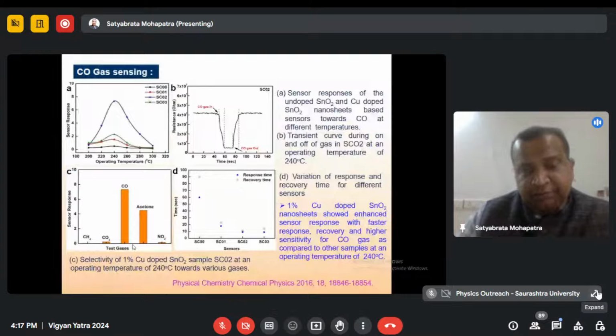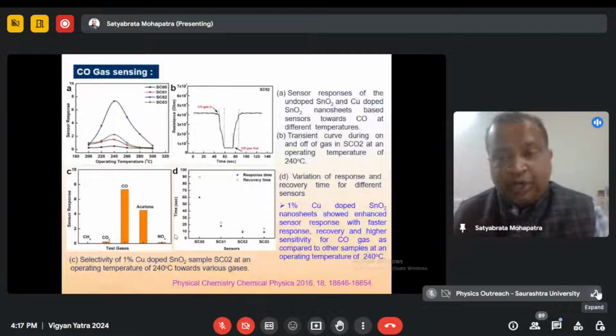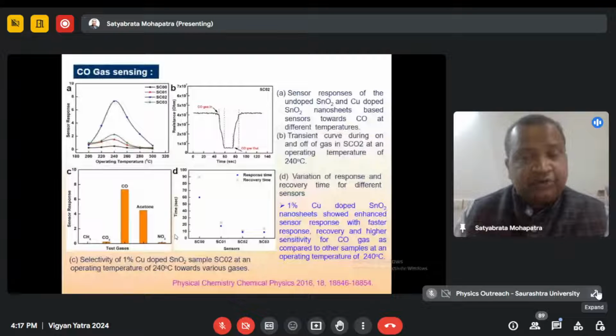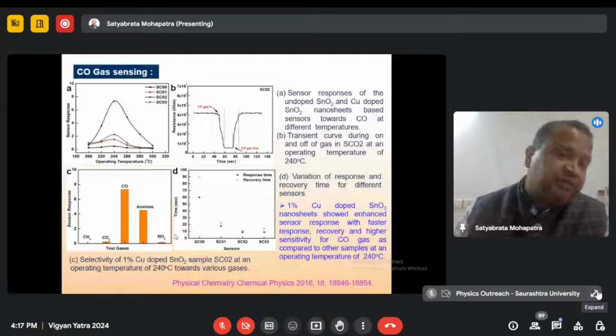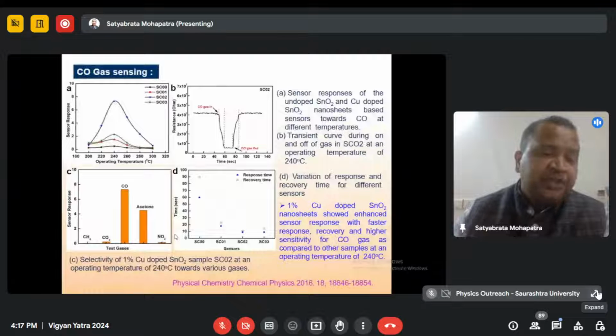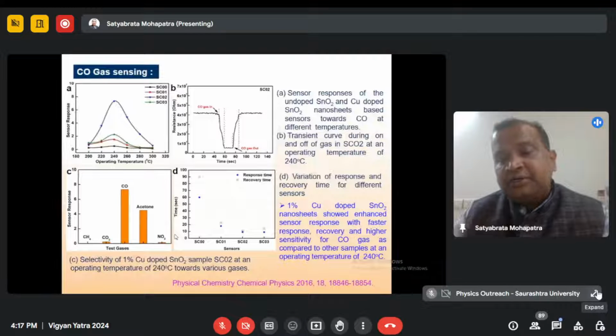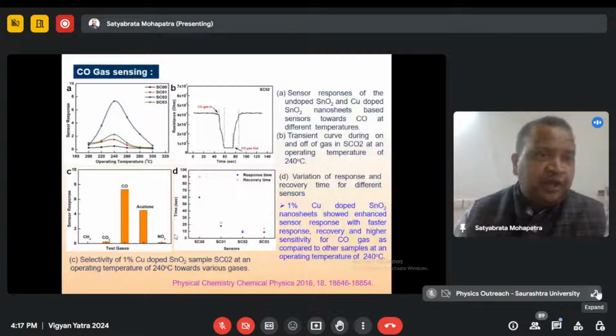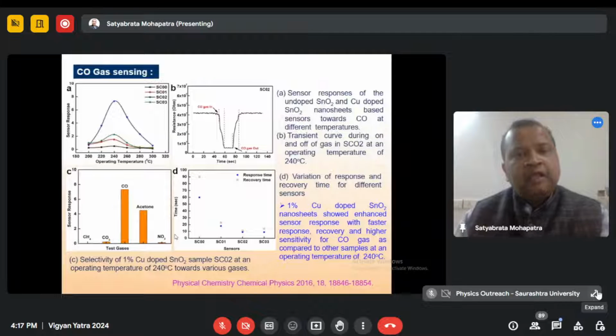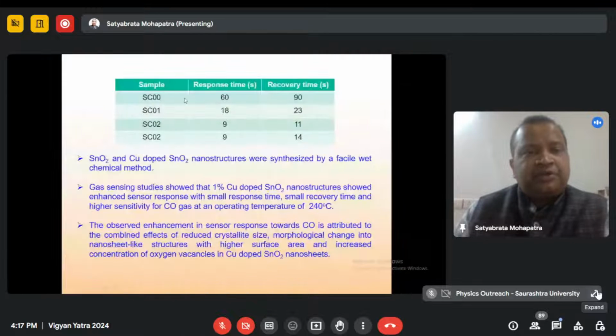Of course, there can be further improvement, and that will show in the next studies, where we go on reducing this operating temperature, improving the sensor response and decreasing the response and recovery time. That's what is needed for the development of an efficient carbon monoxide gas sensor. Now you can see that when you dope with 1% copper, the response time itself decreases from 60 seconds to 18 seconds. Recovery time drops from 90 to 23 seconds.